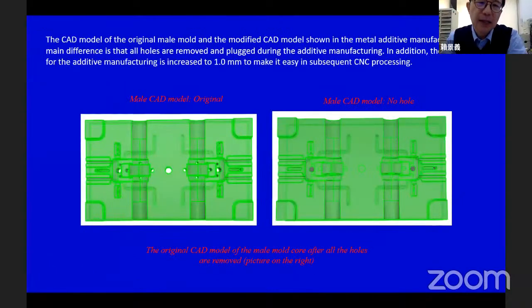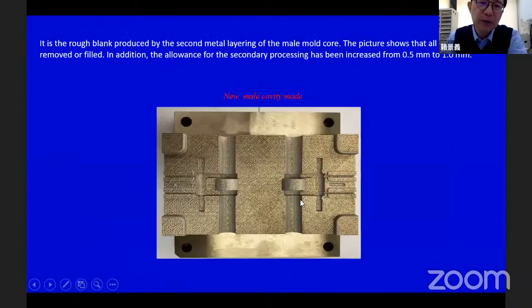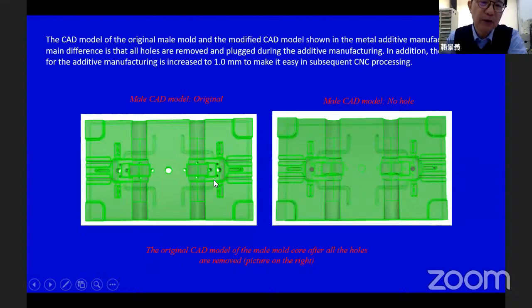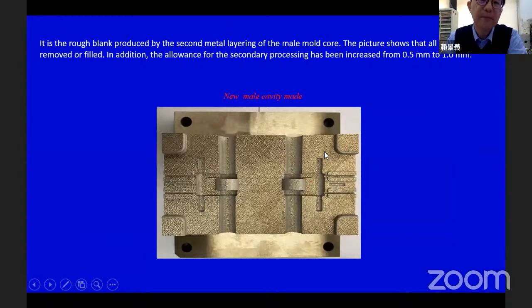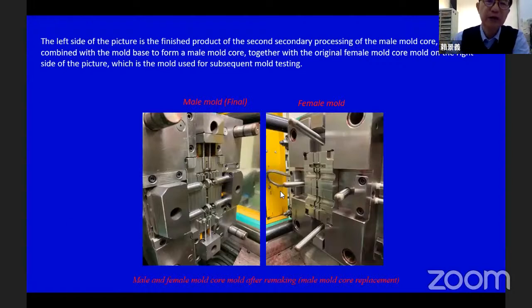So at that time, we needed to reproduce one of the male cores again, and the only difference is that for the original one, for the 3D printing, we already added a lot of holes, but for the new design, we don't fabricate the holes first. So this is the second part we obtained. And after this, when we perform the secondary machining, we drill the holes, and then we can overcome the problem. So this is the final mold we use, for the male one and the female one.